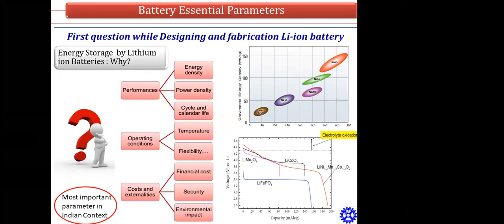Like if you are using a battery in an EV, you need a battery which can sustain more than 45 degrees Celsius. And if you are at a higher altitude like Jammu and Kashmir or Siachen, the temperature is very low, so the battery should start in that cold, low temperature. So the operating temperature is another factor. Third, and the most important thing, is your energy density, power density, and the calendar life, how much it is going. So right now, as I told, LFP and NMC are the major players, apart from LCO and lithium manganese oxide based chemistry.